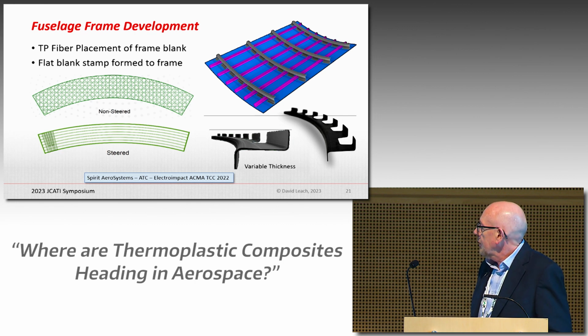So if you imagine the blank that you need for a curved fuselage frame, it would be roughly this shape. And if you took a simplistic or traditional attitude, you would just lay it up in your usual 0, 90, 45 layup. But of course, that means the fiber orientation is effectively changing constantly around the curvature of the frame. So what Electro-Impact did was to enable steered plies.